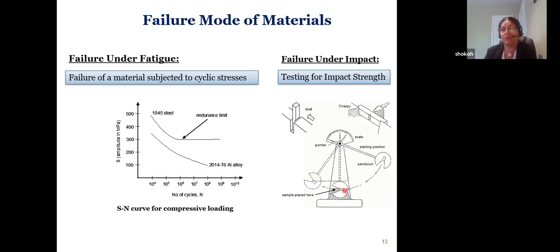And we put the specimen here. We have a hammer, and the weight is based on the ASTM. We have a specific weight and keep it at a specific height. Depending on the specimen, we could heat it up or cool it down, or do it at ambient temperature. And then when you release the hammer, the hammer hits this specimen, breaks it, and tells us how much energy was needed to get that failure.